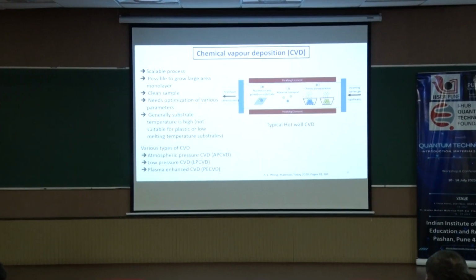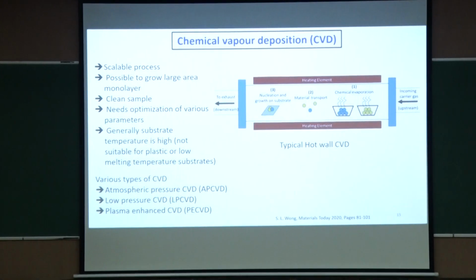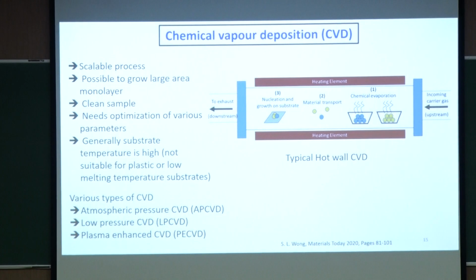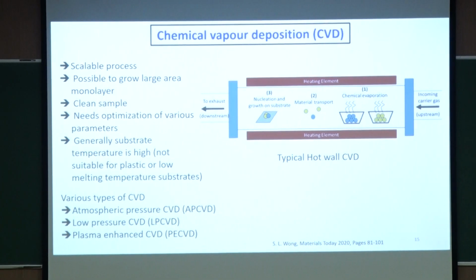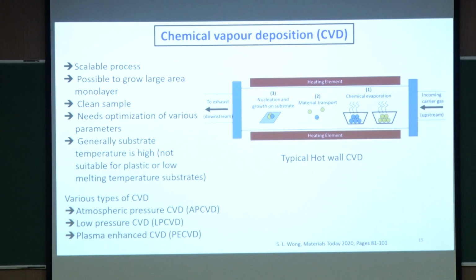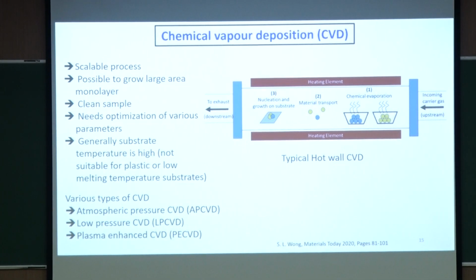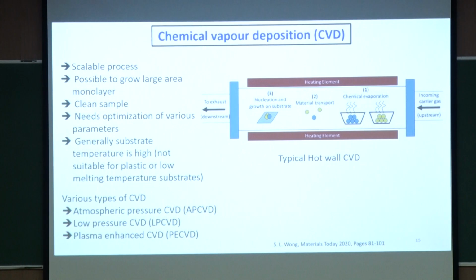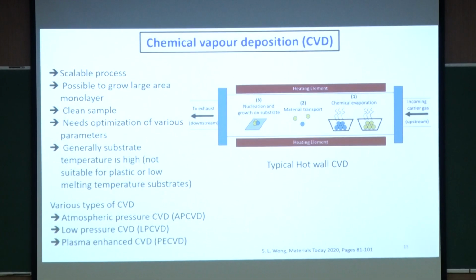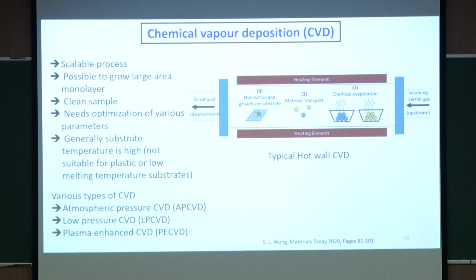Here you can get monolayer without much problem. You can get a pretty clean sample. But the problem is this one: it needs optimization of various parameters, and some of them are very difficult to identify. Sometimes it may be the time of the year, it may be rainy season, and you may not get the monolayer with the same parameters because the humidity of your environment has increased. So there are a lot of known and difficult to identify parameters.